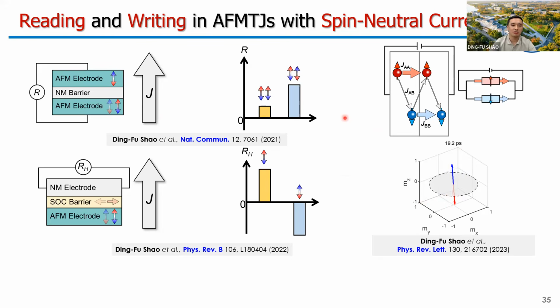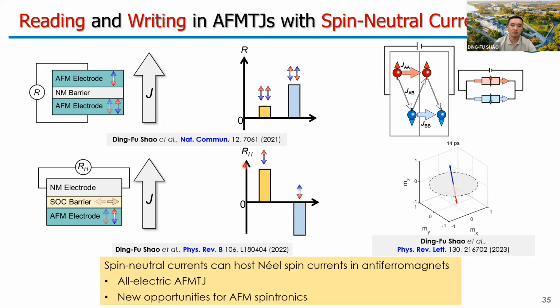Previously, we considered this is due to the antiferromagnetic electrodes we choose having non-spin degenerate film surfaces. But then we recognize that it is due to the spin neutral currents in antiferromagnets hosting the Néel spin currents. Our work offers a very straightforward theoretical framework to realize all-electric antiferromagnetic junctions and may open new opportunities for antiferromagnetic spintronics.